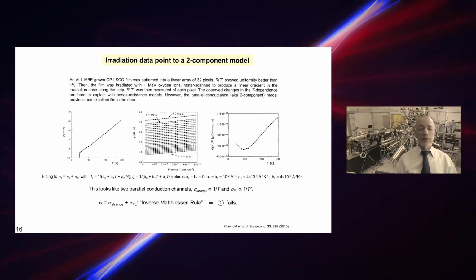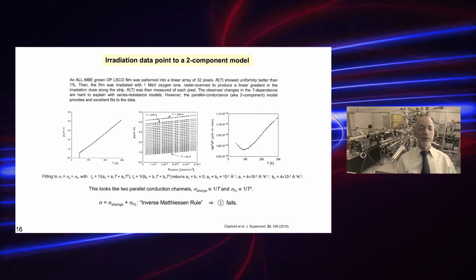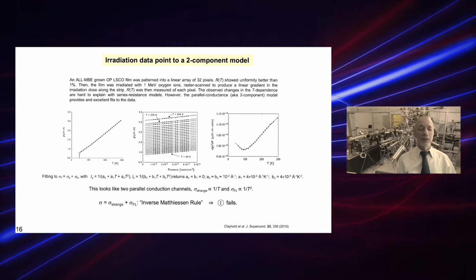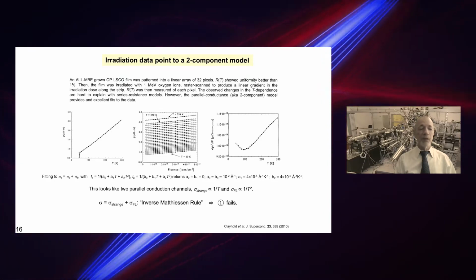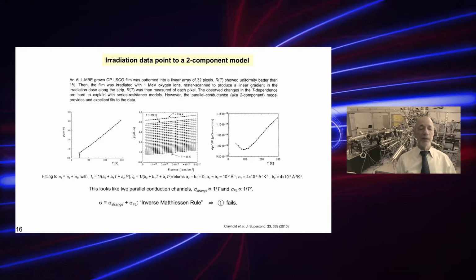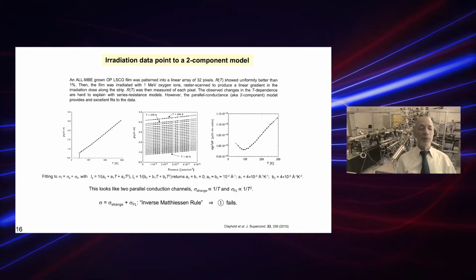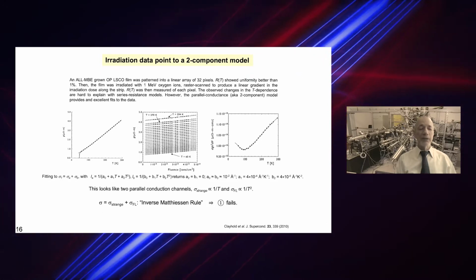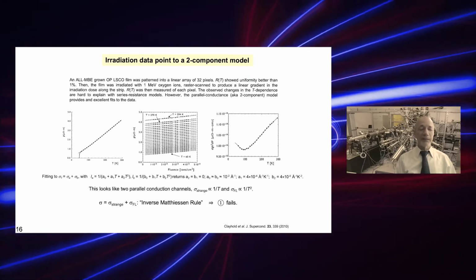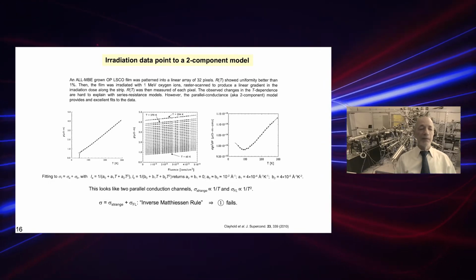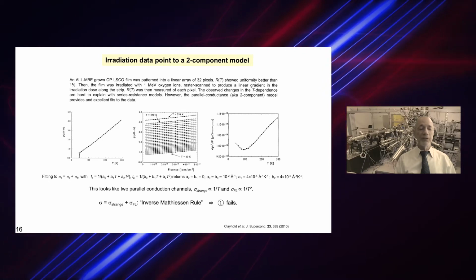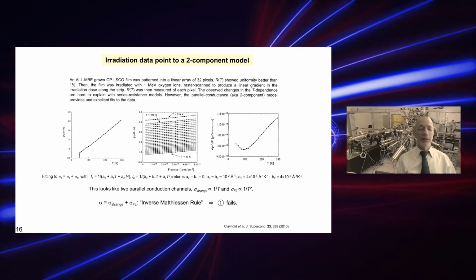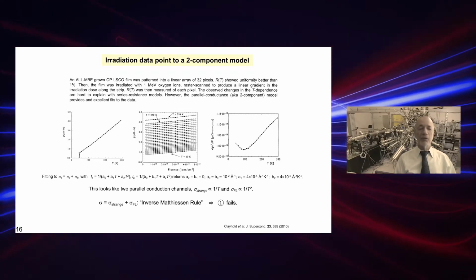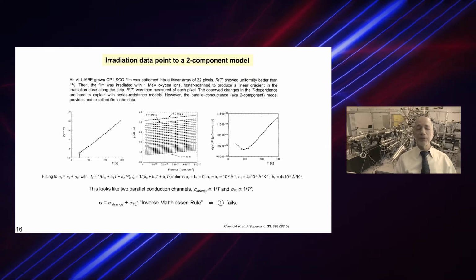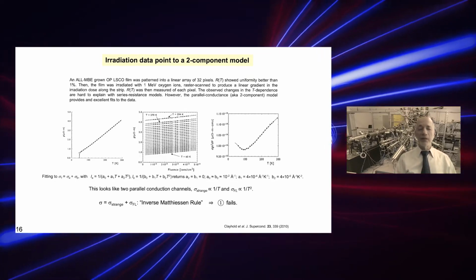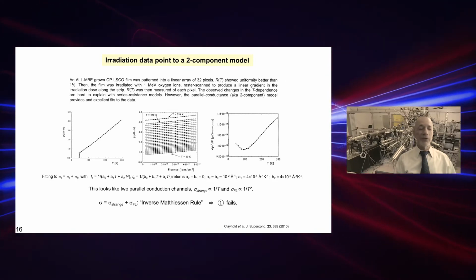This is a systematic experiment on the effects of disorder that we did about a decade ago. So what we did is we picked an optimally doped lanthanum strontium cuprate film and then irradiated it with 1 mega electron volt ions. We did this in a combinatorial way. So we patterned the film into 32 pixels and then exposed each pixel to a different, exactly known dose. And that gave us a combinatorial library of 32 samples, each with a different irradiation dose and therefore with a different level of disorder.